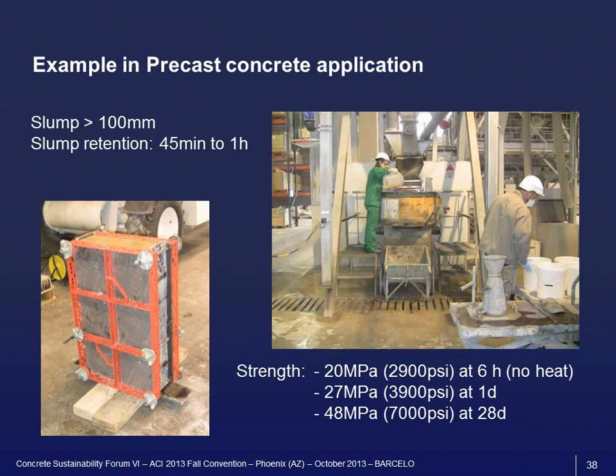And here we have an example on concrete made for precast application with this cement. So we had a slump larger than 100 millimeter, slump retention 45 minutes to 1 hour for this precast application. The strength development, very interesting. So 2900 psi at 6 hours with no heat, 3900 psi at 1 day, and 7000 psi at 28 days.